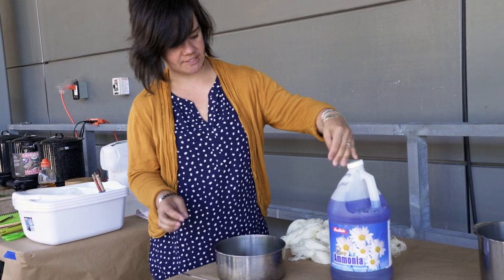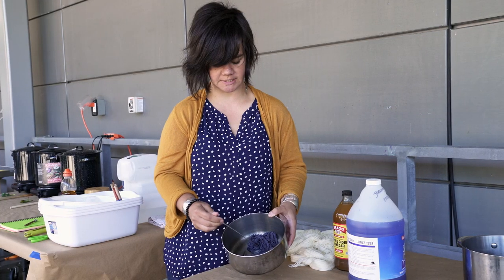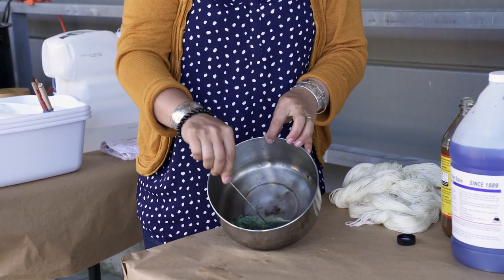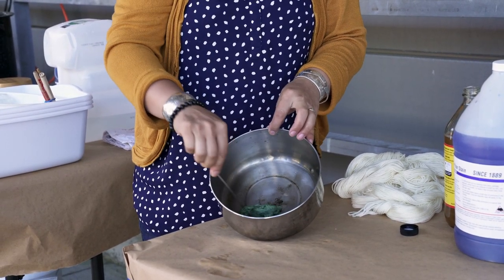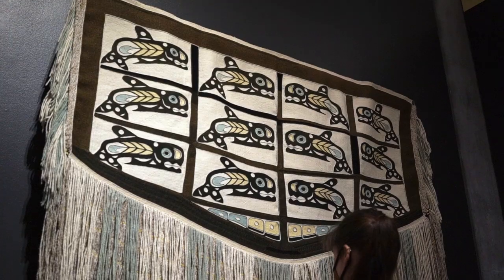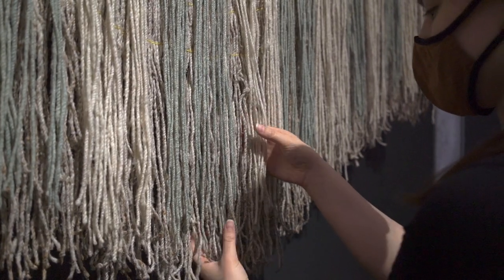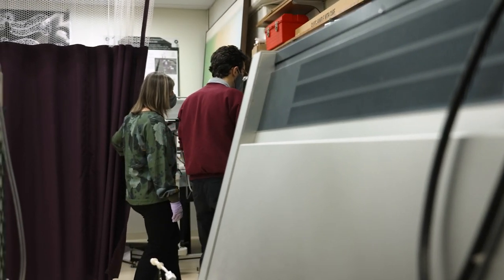This is our hypothesized method of getting a blue liquid, and we've been using this a long time. From what weavers tell us, one of the ways still used is you take a copper pipe, put it in ammonia, and let it soak. You'll get this kind of boring, steely, grayish color — not a color that I would weave with. But if you dip that in vinegar, changing the pH, you get kind of this nice minty green. This is a color we want to weave with. Interestingly, there's a robe on exhibit right now that has that minty seafoam green in the fringe. We used our XRF, our X-ray fluorescent spectrometer, hoping this was the copper color — and it doesn't have any copper in it. So there was some other way they were getting this minty green besides copper.